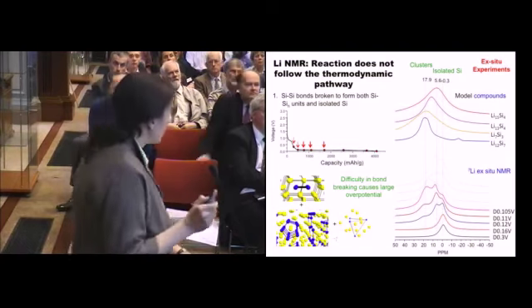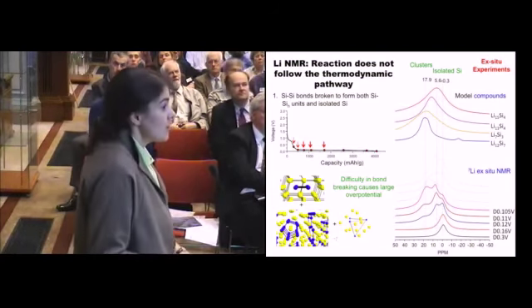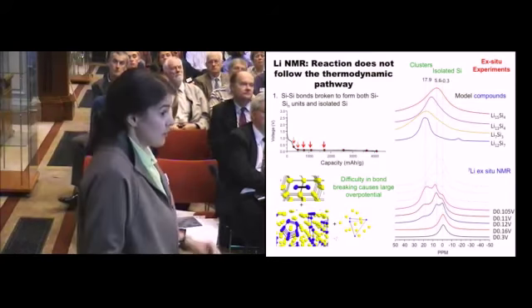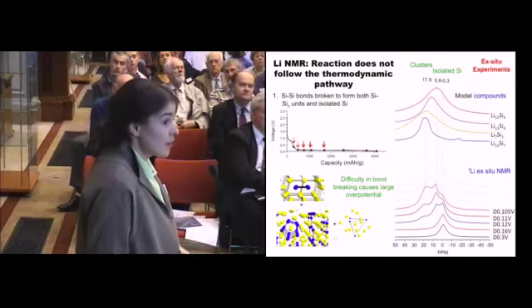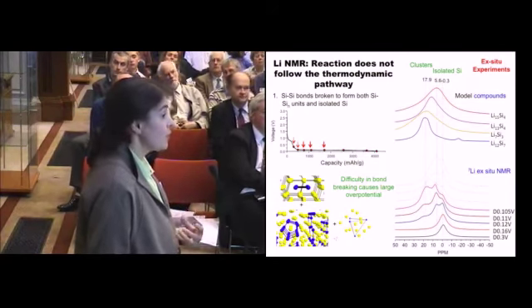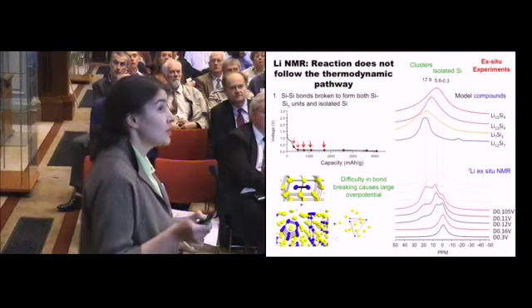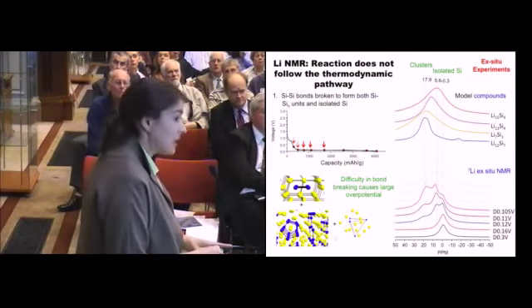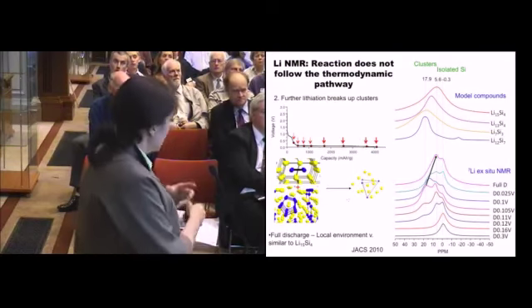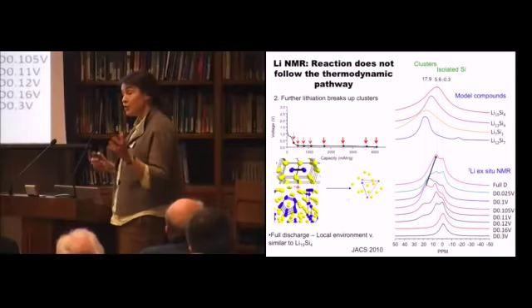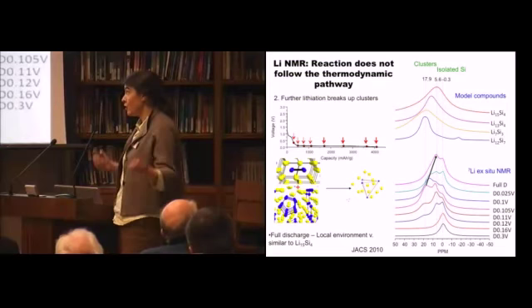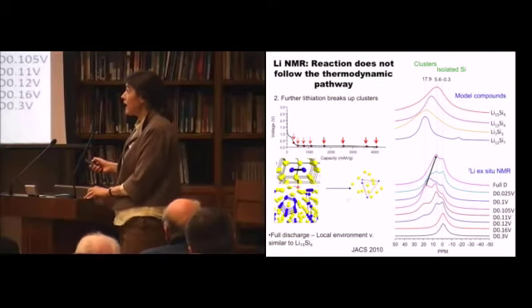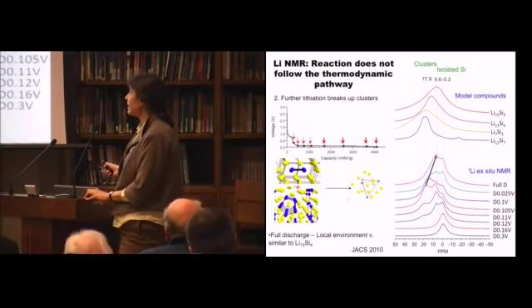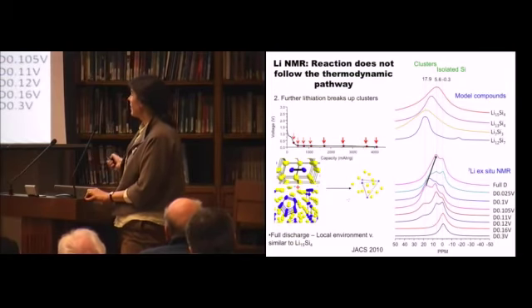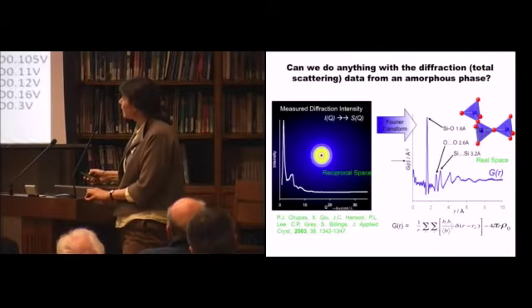And this is not the same route that the battery took. It's not the thermodynamic route. If you had a thermodynamic route, you would expect first of all the clusters to form, and then you'd form isolated ions. But instead, because it is so difficult for lithium to break silicon bonds, you go straight in and aggressively rip apart the silicon, and you form both clusters and isolated ions. And at the end of the reaction here, you then break the clusters apart, and you form isolated silicon ions.